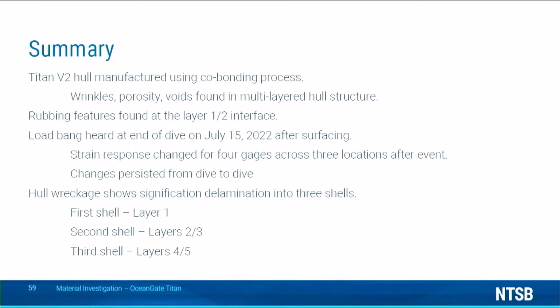So to summarize, the Titan V2 hull was manufactured from pre-preg unidirectional carbon fiber using a co-bonding process with multiple adhesive interfaces. Examination of the hull material revealed waviness, wrinkles, porosity, and voids within the multi-layered structure. A recovered piece of the hull exhibited features consistent with rubbing. Examination of strain gauge data after dive 80 event showed a change in the mechanical response of the hull for 4 strain gauges across 3 locations of the hull. Those changes persisted from dive to dive.